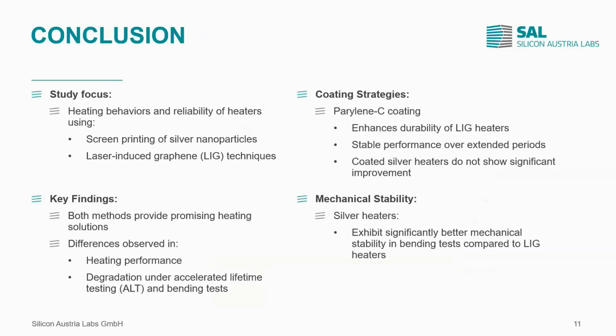So let's sum this up. We have seen a comparison of printed silver heaters and LIG heaters, their heating performance, coated and uncoated with Parylene-C. Silver has shown to be more stable compared to LIG, at least for accelerated life testing. The LIG heaters need to be coated.